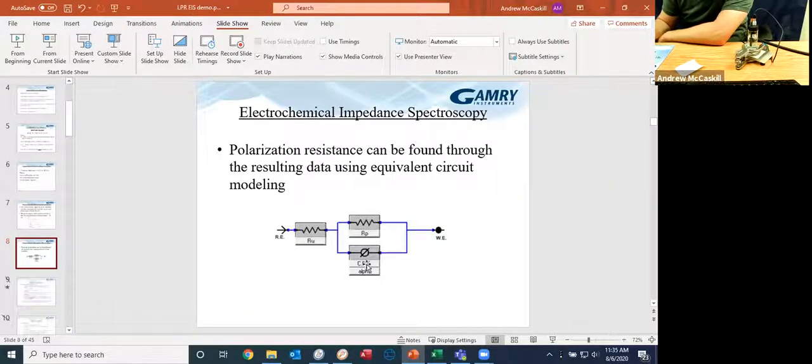This represents the resistance and the capacitance seen on the surface of the electrode, the surface of our working electrode, that little 1 centimeter squared surface of steel exposed. So maybe you can visualize that a little bit. You can see that this right here is your solution. This is the surface of your electrode. The solution is purely resistive.